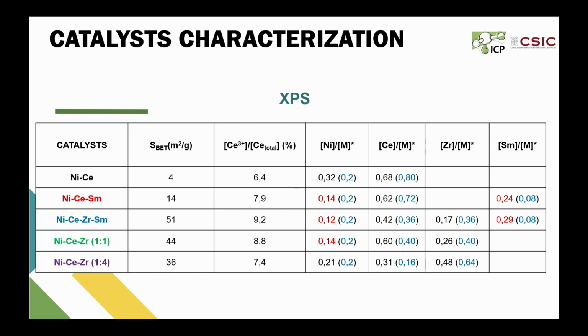XPS quantitative analysis data show that all catalysts with zirconium obtain an enrichment in ceria at the surface. The addition of samarium slightly increases the degree of reduction of ceria, and the quantification of nickel indicates that a significant part of it could be in the structure in a non-surface state, except for the nickel ceria.